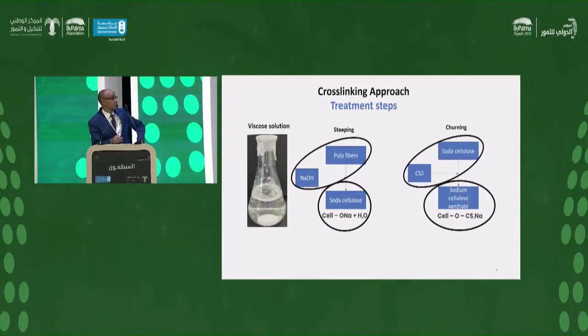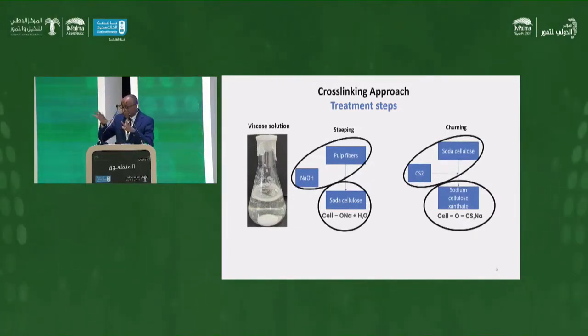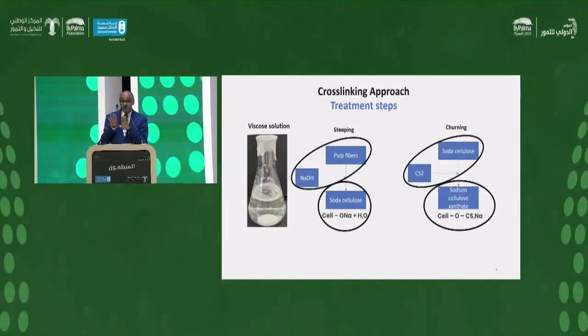After that, we use carbon disulfide to open the link and to have more functional groups to be treated and to cross-link it when we have the contact in the cross-linking media. And we obtain soda cellulose or sodium cellulose xanthate.